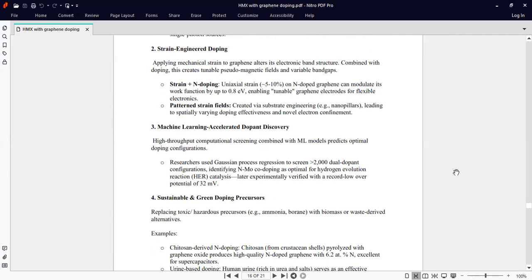Strain plus N doping, which is uniaxial strain on N-doped graphene, can modulate its work function by up to 0.8 electron volts, enabling tunable graphene electrodes for flexible electronics. The other is a patterned strain field created via substrate engineering, leading to spatially varying doping effectiveness and novel electron confinement.